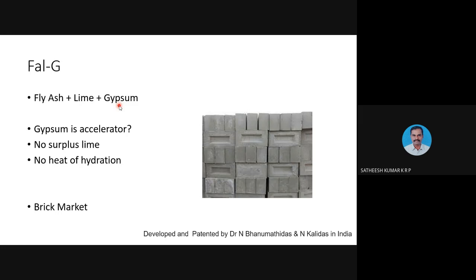But what happens when we combine fly ash, lime, and gypsum with cement is that gypsum acts as an accelerator for one component, whereas it acts like a retarder for the other component. But the ultimate product is only going to be the calcium silicate component. Using these two things together is like using two compatible binders in a single matrix, which will give the same ultimate product.